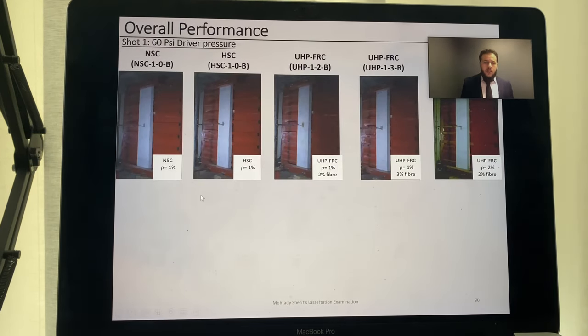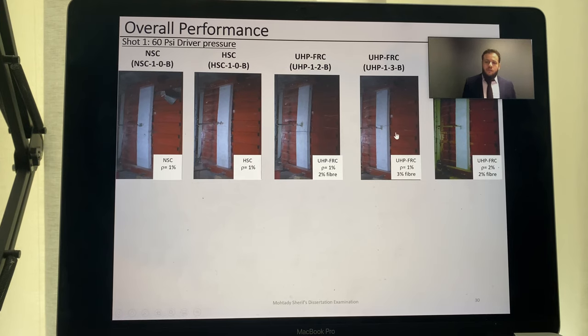Under the first blast shot, traditional concrete experienced higher deformation and damage compared to the UHPFRC panel with 1% reinforcement and 2% fiber, which showed a smaller damage zone and more localized behavior. Increasing fiber content to 3% produced better damage distribution and lesser deformation. The specimen with 2% fiber and 2% reinforcement showed even better overall performance.